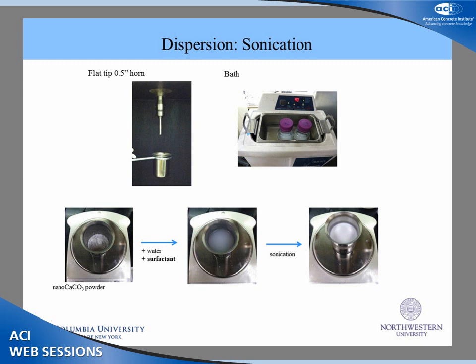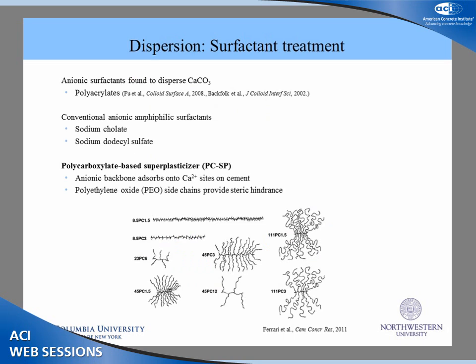So in this process, you start off with the nanocalcium carbonate dry powder, add water, and then sonicate, and then you're left with a suspension. And that suspension is what you ultimately add to your dry ingredients, your cement and your fly ash, to create your paste. Now, this is a mechanical method, and for most cases in dispersing nanomaterials, you need the aid of surfactant. And in the case of calcium carbonate, that was the situation. So in literature, anionic surfactants have been found to disperse calcium carbonate. So in our study, we tested conventional anionic amphiphilic surfactants and also superplasticizers, including a polycarboxylate-based superplasticizer, or PC.